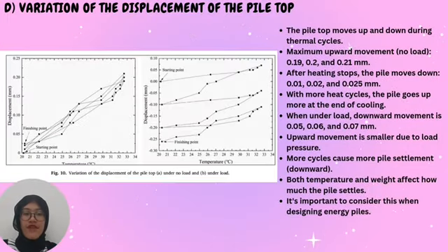On this slide, we look at the variation of the displacement of the pile top during thermal cycle. As shown in the graph on the left, the pile top moves both up and down as it experiences heating and cooling. Without an applied load, the maximum upward movement of the pile top reaches about 0.19, 0.2, and 0.21 mm. However, once the heating process stops, the pile tends to move downward with displacement of approximately 0.01, 0.02, and 0.025 mm. When the number of heat cycles increases, the pile top tends to move upward more significantly at the end of the cooling phase.